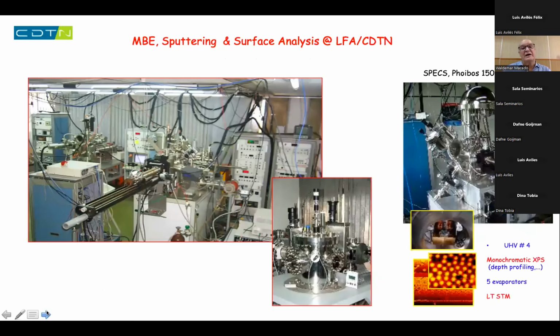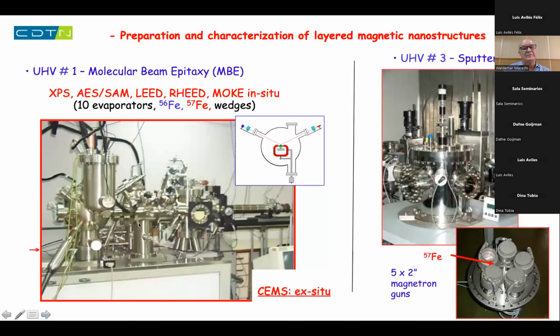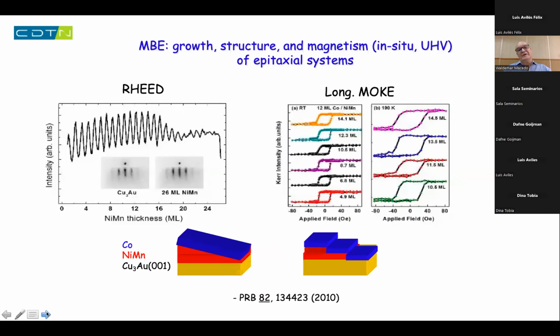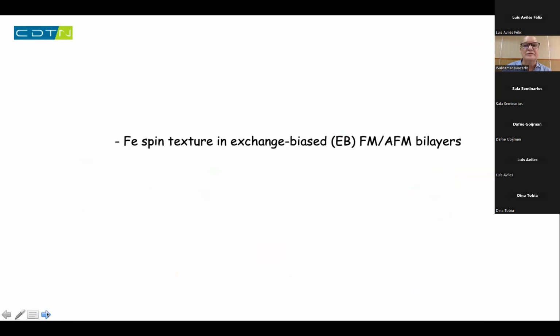Okay, based on that, these are the systems we have in our lab. We have a lot of equipment to grow films, do surface physics and prepare samples. You can prepare samples with iron 57 by molecular beam epitaxy in these systems, or even by sputtering in this other system, okay? This is the system where we play with iron 57 in the samples. We can get very nice epitaxy in different systems. And this is an example of very nice layer by layer growth, but in a system where we don't have iron, so you cannot use Mössbauer spectroscopy here. But let me go to the results I want to show you today.